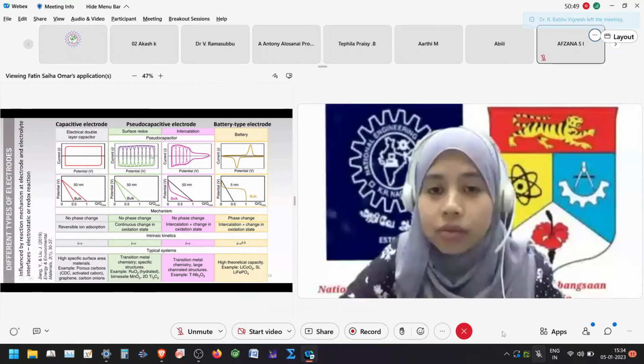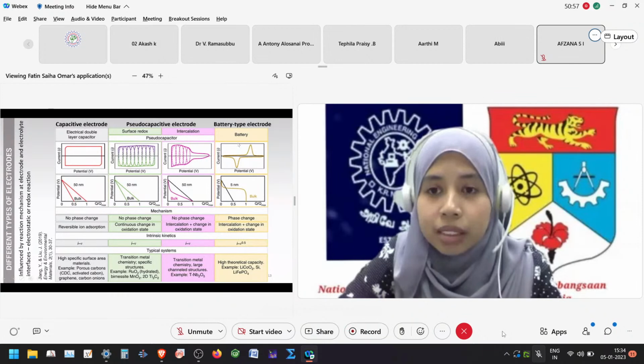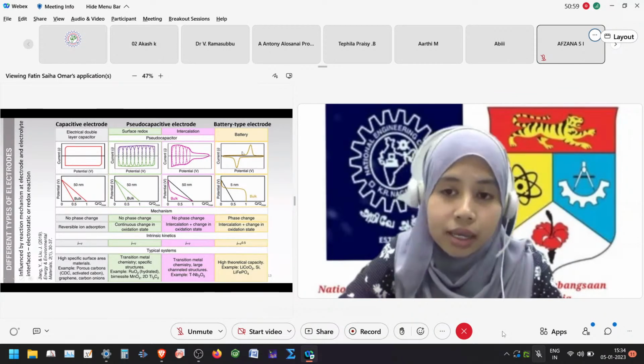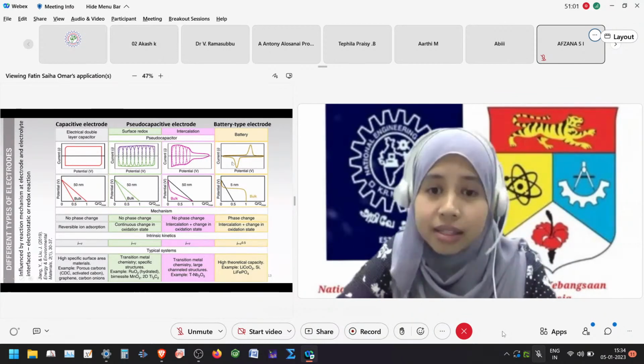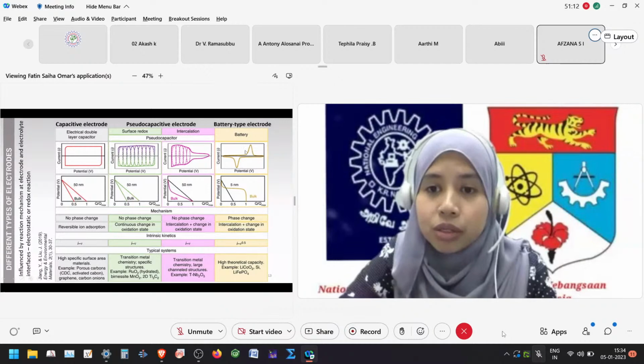So it means that the intercalation happens. But it is different with battery type electrode. There are peaks at the anodic and cathodic. The peaks are intense, so we can clearly see the difference between the broad peaks at the pseudocapacitive electrode and the intense peak at the battery type electrode.